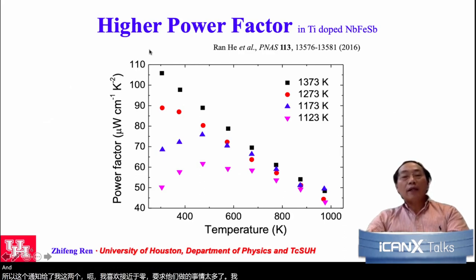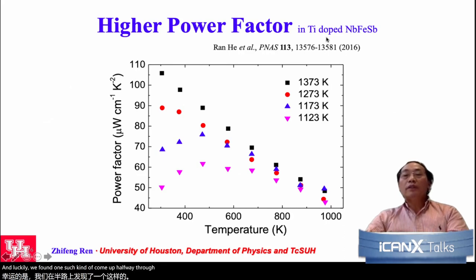And then luckily we found one such compound, half-Heusler, which is titanium doped niobium iron antimony, with different amounts of titanium dopant. And then we were able to get a power factor over 100 at room temperature. This is outstanding.